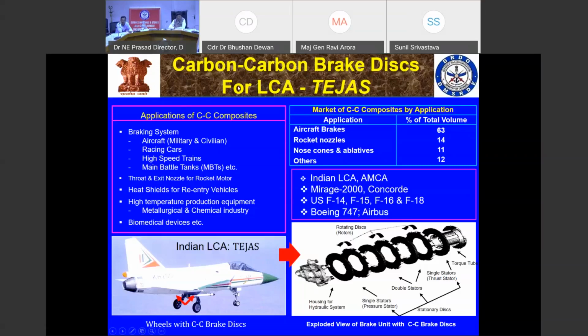Carbon as an element is the only one which retains its frictional properties even at very high temperatures. Most of the metals, even oxides and carbides, become sticky when the temperature rises very near to the melting point, or even 0.7 to 0.8 times the homologous temperature. That is the melting point expressed in degrees Kelvin. So carbon is the one which retains its frictional properties even beyond 0.8 Tm. So the carbon-carbon composites are developed and they are qualified.